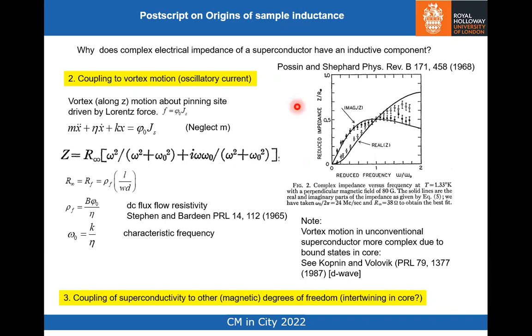So here we're considering vortices that are pinned, so they are subject to some restoring force about their pinning site. Their motion is driven by the Lorentz force, or is it the Magnus force? And they're subject to some viscous relaxation process. So the ratio of K over eta defines a characteristic frequency. This thing out the front is the DC flux flow resistivity that you would get if you apply sufficiently strong forces to depin the vortices. There's this ancient paper in which this kind of stuff was seen in the real part and the imaginary part of the impedance in some normal metal, and I've forgotten what it is.